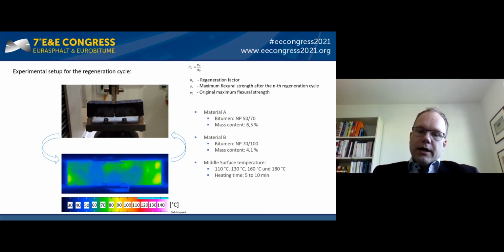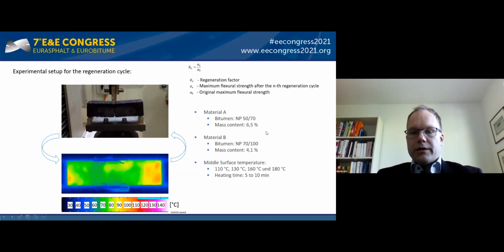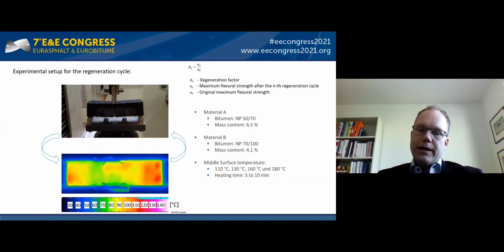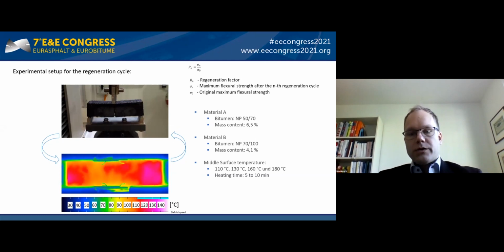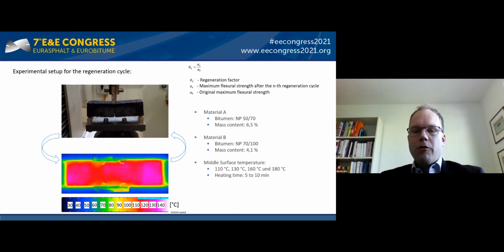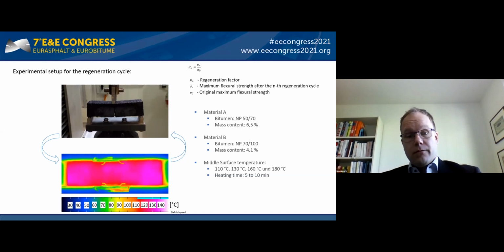For each regeneration cycle, the maximum flexural strength was calculated, and out of the maximum flexural strength in the regeneration cycle, a regeneration factor relative to the original maximum flexural strength was calculated. Two materials were used for the experimental series, one surface course material and one wearing course material. The specimens were heated up to four different temperatures, 110, 130, and 160 degrees, and also a maximum temperature of 180 degrees, just to see if the temperature will affect the regeneration and the binder aging.